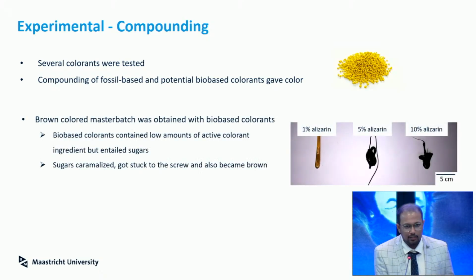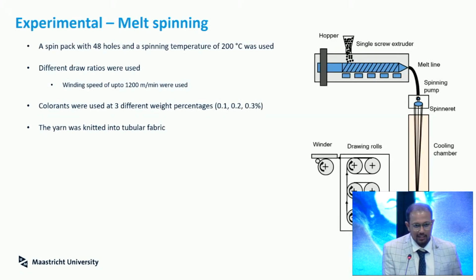But when I was using the actual bio-based variants, I had a lot of issues because of the degradation of these colorants, because they had some sugar inside, which was caramelizing and getting stuck in the machines. And in the end, as you can see in the picture here, it was just brown, which was definitely not the color we wanted.